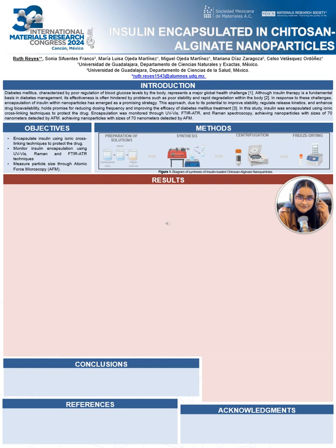At this stage, we can perform DLS, AFM, and UV-Vis analysis. However, for Raman and FTIR analysis, we need dry nanoparticles. To achieve this, we centrifuge or cool it, protect it with a cryoprotectant, sucrose, and then lyophilize it, preparing it for analysis and storage for future release studies.